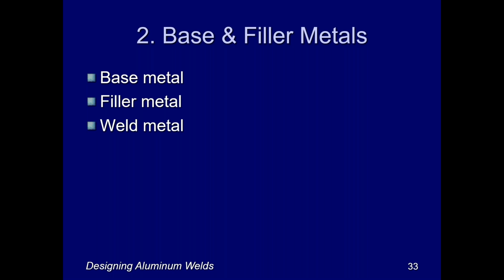And then when those two parts get melted together in some sort of a mishmash or mixture, that's referred to as the weld metal. And its composition is going to be somewhere in between the base metal and the filler metal, depending upon how much dilution of the base metal or the filler metal occurs in the joint. And that's going to be a function of a lot of factors, and yet that's going to determine the strength of the joint.